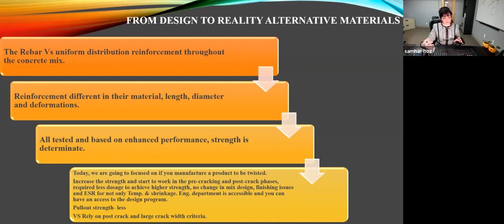So today, we're going to focus on what you will get when you manufacture a product with a twist along its full length. Now, this allows the product to perform in the pre-cracking phase in addition to the post-cracking phase. So this allows the strength required to be met by even lower dosage. And it also allows the product to achieve higher strength.